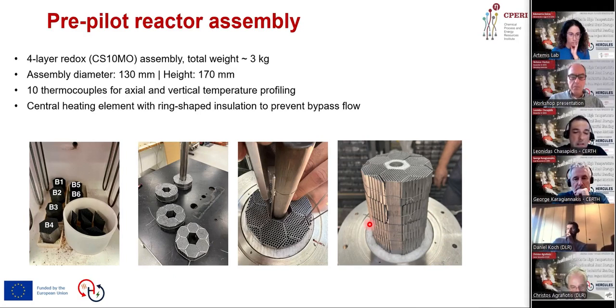And around it, we placed a layer of insulation to prevent unwanted gas flow through the center and to reduce the radial heat losses. In total, 12 temperature measurement points were acquired from 10 thermocouples that were inserted axially and vertically through the structure. The configuration provides a detailed picture of the internal temperature distribution, both during reduction and oxidation. And it also helps us identify any thermal gradients or uneven heating, which are key issues for scaling up the technology. Next slide, please.